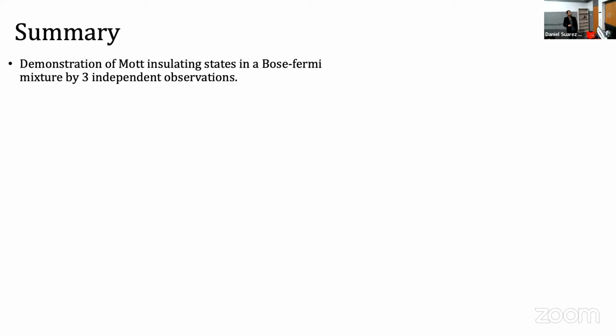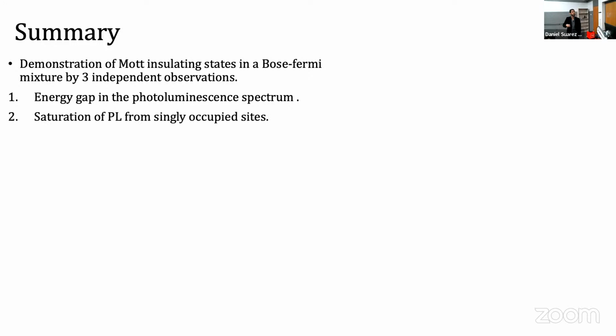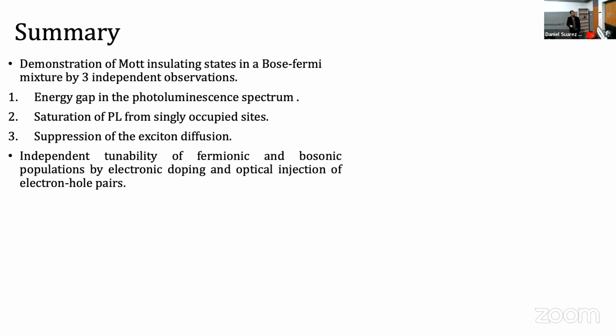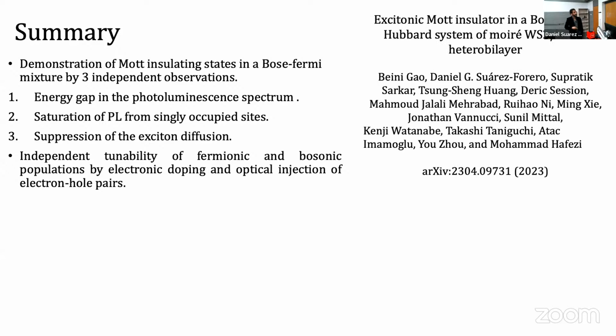So let me finish by summarizing the results. We then demonstrated Mott insulating states in a Bose-Fermi mixture of particles in 2D, in heterostructures of 2D materials, benchmarked by 3 observations. The first one is the energy gap in the photoluminescence spectrum, the saturation of the PL from singly occupied sites, and the suppression of the diffusion of excitons in this material. And also some nice potential of these devices is that one can control in real time the population of bosons and of fermions completely independently.